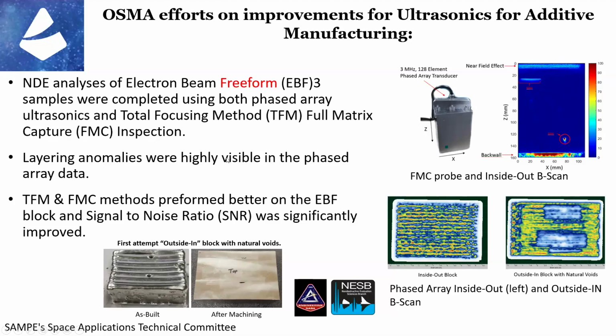But certainly for certification for ultrasonics, especially pre-heat treatment, I think there's still a lot of work to be done with ultrasound. Although our initial results are pointing more toward full matrix capture versus phased array, which does make some sense because in a full matrix capture system, you're effectively collecting every ultrasonic pulse that you could. Whereas in a phased array system, the phasing of the system has to be set up ahead of time and just caused us some interesting issues. I'm not saying by any means that they can't be tackled. They're just still in work.